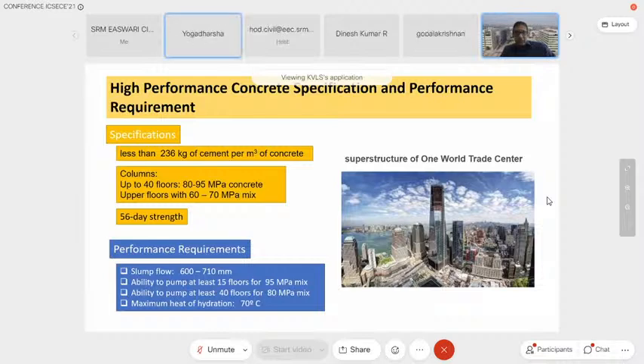The other performance requirements that were given were that concrete had to achieve a flow of 600 to 710 millimeters. That means the concrete had to be very flowable, and the concrete had to have the ability to pump for at least 15 floors for the 95 megapascal mix, and it had to be pumpable up to 40 floors for the 80 megapascal mix. So this is a performance specification on the fresh concrete that is being put in place. This is the requirement that it had to meet. The maximum heat of hydration was specified at 70 degrees Celsius. So these are performance requirements and specifications that are put in place. Now, how the contractor achieves these specifications and these requirements is left to the contractor.